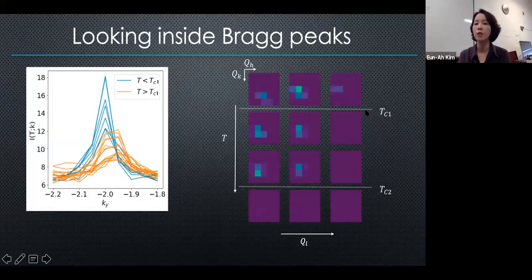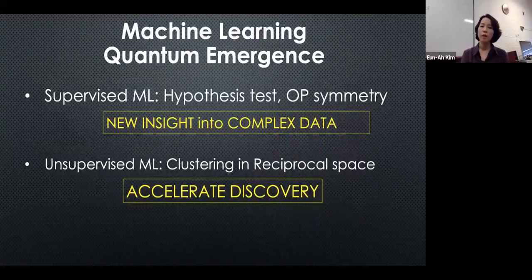Now, with the lower transition, though, it's not the new peak showing up so much, but the same peak is changing its shape. And this shift of the peak shape is the only way intra-unit cell changes, such as this kind of distortion, can manifest itself. And this was the first time this was detected through X-ray measurements. And the only reason why we could be confident that this is a meaningful thing was because we had statistics over thousands of Brillouin zones. So that's a truly new discovery that we were able to achieve, and we're very excited about this.